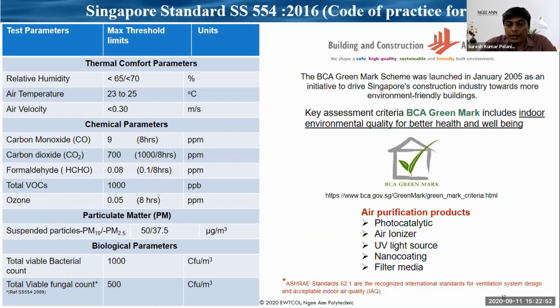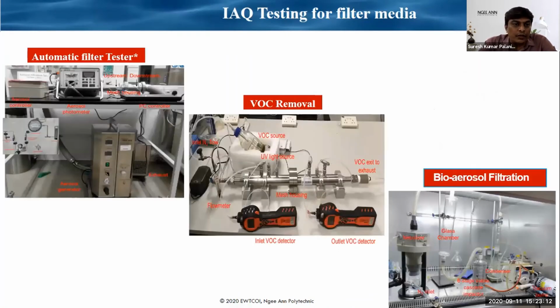So we are in the range of testing different kinds of air purification products like photocatalytic-based air ionizers, UV light sources, nano coatings, and filter-based media. We are open to testing any of these products with respect to the standards of Singapore. For IAQ testing of filter media, we have an automated filter testing system in our lab, which can measure the filtration efficiency and the pressure drop of filters with particle sizes from 0.1 micrometer to 0.3 micrometer, both solid